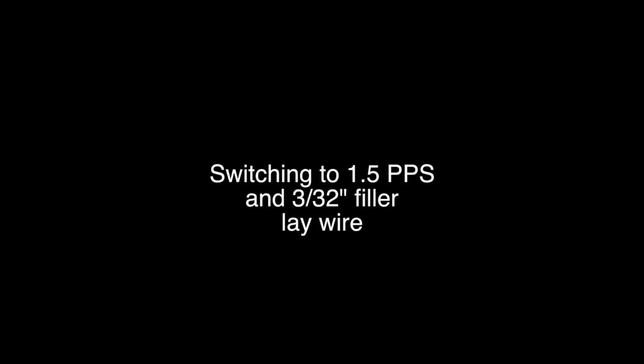So that helped. What's going to help even more is switching to the pulser. So the thing with pulse is sometimes it can really control or minimize penetration. That's one thing you can do with pulse. A lot of times on square tubing, whether stainless or carbon, you don't necessarily want to penetrate all through the backside. You'll draw oxides into the puddle and the puddle gets all squirrely like it did with me. So the pulsing, especially with lay wire, can really help you to control the amount of penetration. It's done a lot on stainless steel, especially outside corner joints on stainless steel sheet metal. If you get your pulser set just right, you can zip along on an outside corner joint and really control penetration and not sugar the backside.